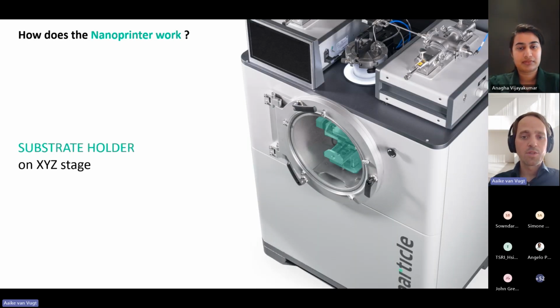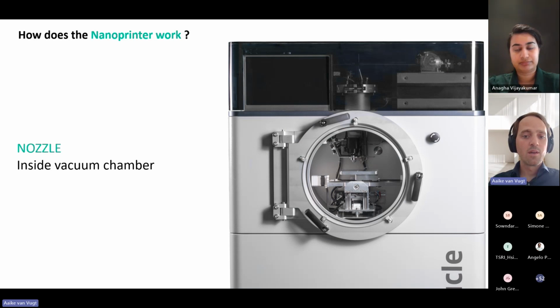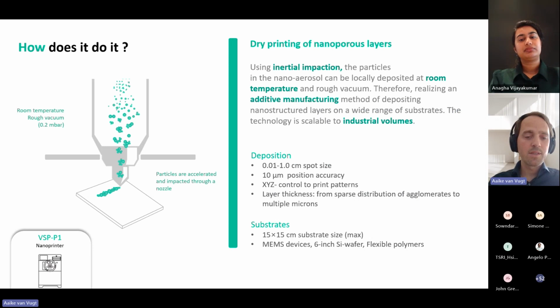Next to the sources, there is a stage on which you can apply your substrate, which has XYZ control. And inside this chamber where the stage is, we operate at a lower pressure to basically impact the particles onto the support. In the stage, there are also 2 camera modules to verify what you have printed, but also to align the stage to the right starting position. So the printing process works by creating a big pressure difference upstream and downstream. Upstream, coming from the nanoparticle source, is roughly at 1 atmosphere, while downstream we have this rough vacuum. It's 0.2 millibars, and because of this pressure difference and a small nozzle, we get the acceleration of the gas flow almost to supersonic speed, which helps us to impact the nanoparticles on this 2D substrate.